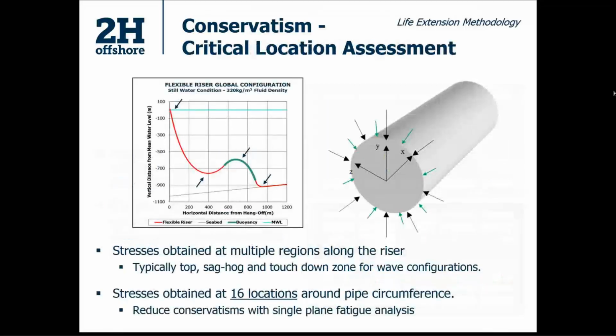Another area is looking at those critical locations, how those critical fatigue locations that we identified in our global analysis, we look into in more detail in our local analysis, how we can calculate those stresses and how we can also see that the bending is not always happening in one plane. So instead of using that as a conservative approach that might have been done at design, we can see how the bending and tension can be applied in up to 16 locations around the pipe circumference.